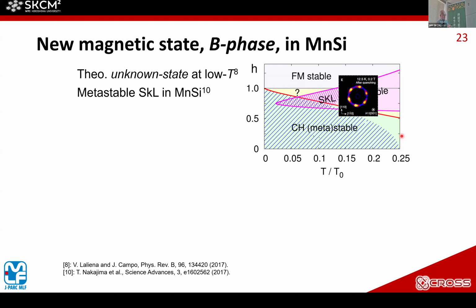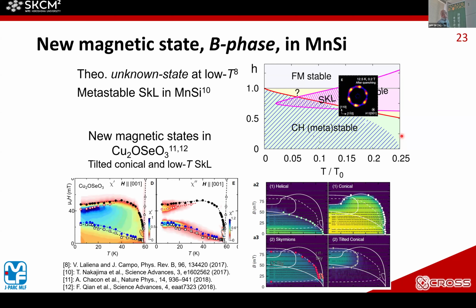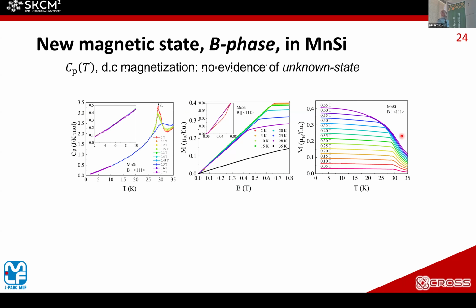And also in other materials. So this is also a cubic chiral material, Cu2OSeO3. Even in this material, the tilted conical state and also the low temperature skyrmion lattice were observed. So there is something in the low temperature region, but in manganese silicide, at this moment, we don't observe anything except the metastable skyrmion lattice. So what is this unknown state? Is it real or not? Then we try to find this unknown state.